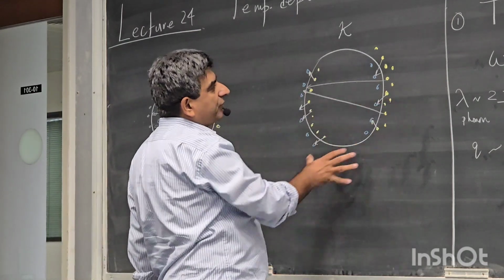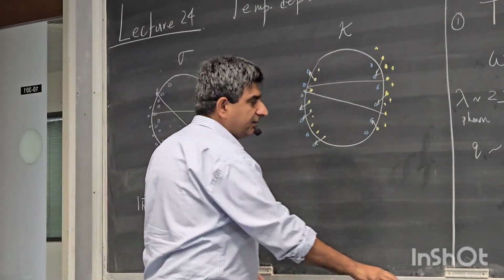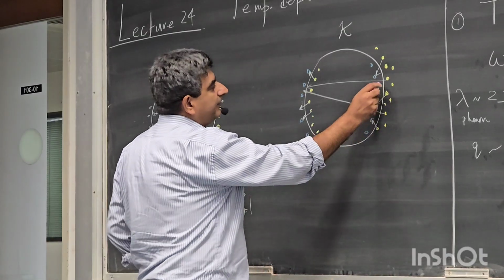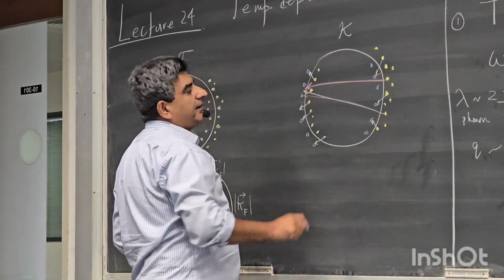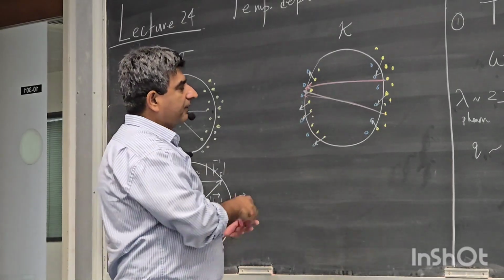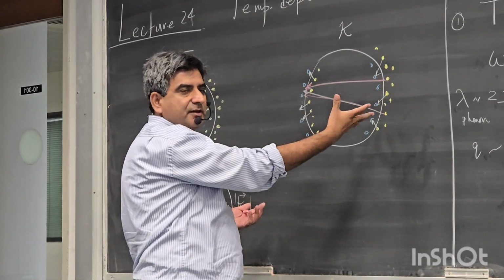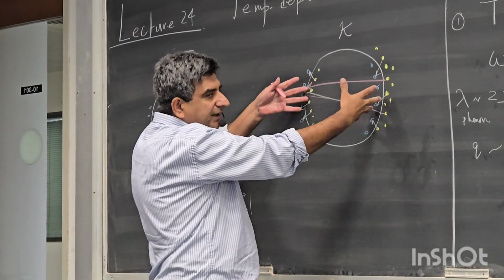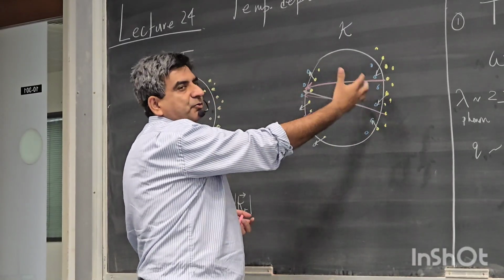As far as thermal conductivity is concerned, at high temperatures, you can still have these backscattering processes because phonons are available at this temperature. Phonons with such a large wave vector are already available. So you can have these momentum reversal processes.